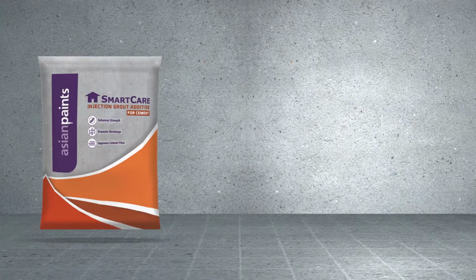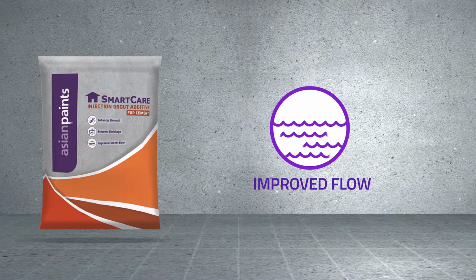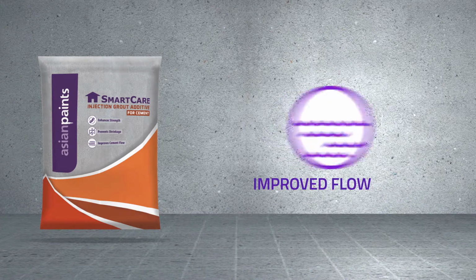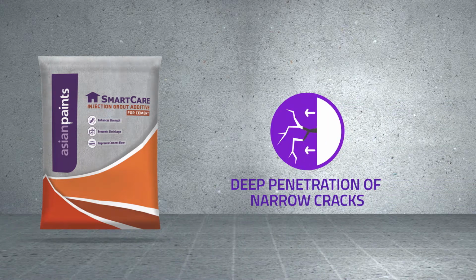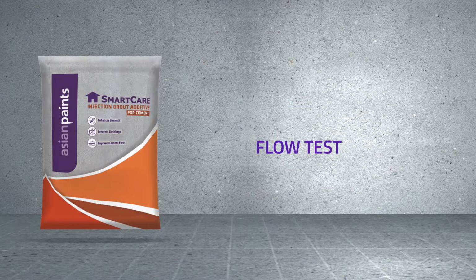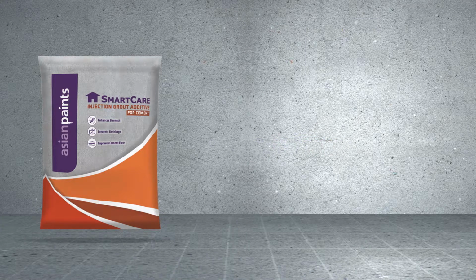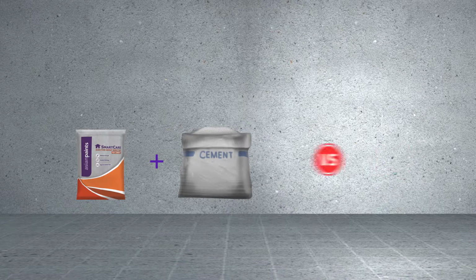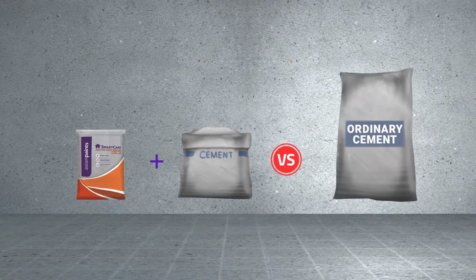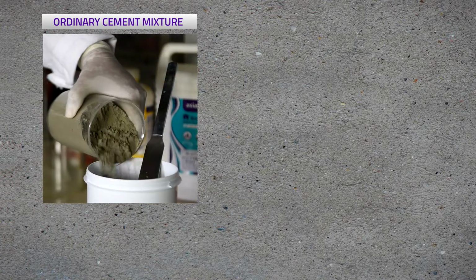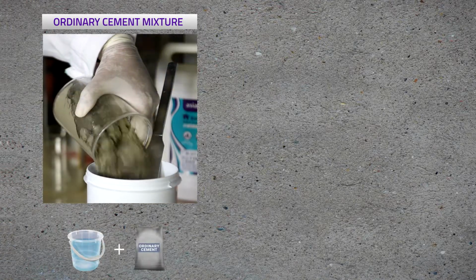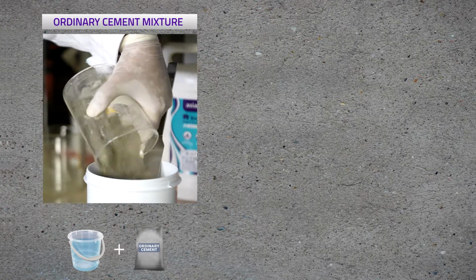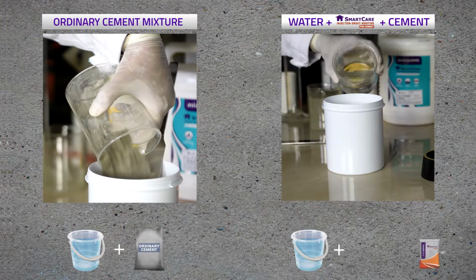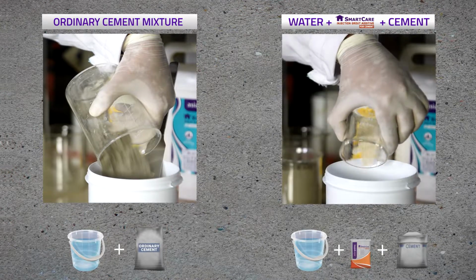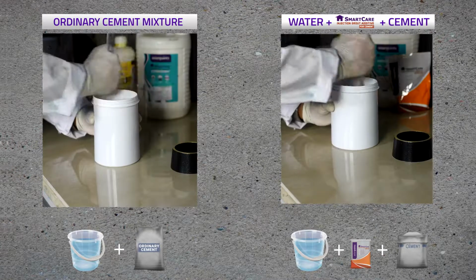The next feature of SmartCare Injection Grout Additive is that it improves flow by producing a free-flowing and penetrating grout. Only a material which is free-flowing can enter the micro crevices and plug them, thereby solving the problem of leakages, etc. The flow test demonstrates this benefit of using SmartCare Injection Grout Additive with cement in comparison to using only ordinary cement. For this, we first create 2 mixtures. One mixture containing water and ordinary cement in a ratio of 0.4:1, that is 0.4 parts of water with 1 part of cement, and another similar water-cement mixture to which SmartCare Injection Grout Additive is also added as per the recommended ratio.